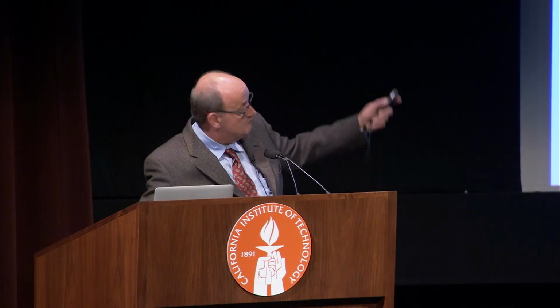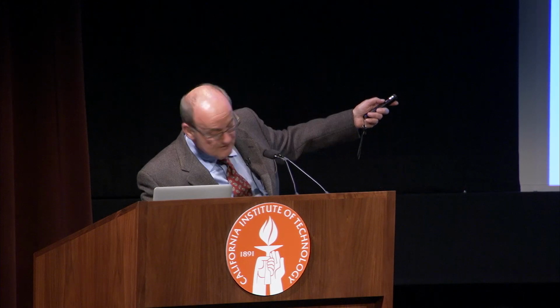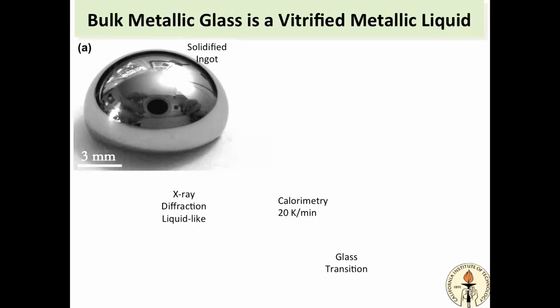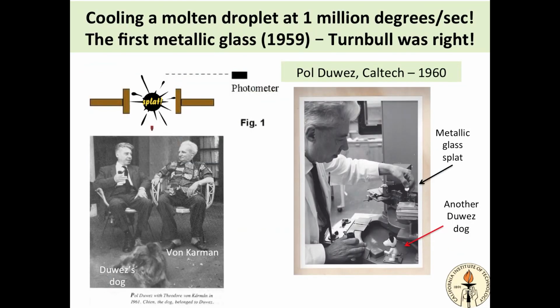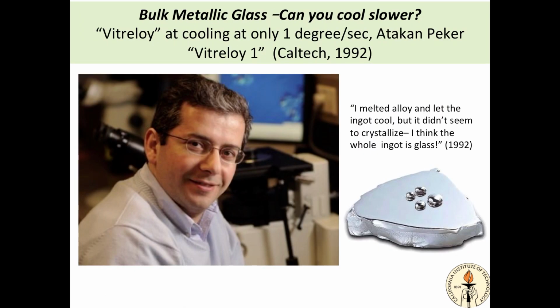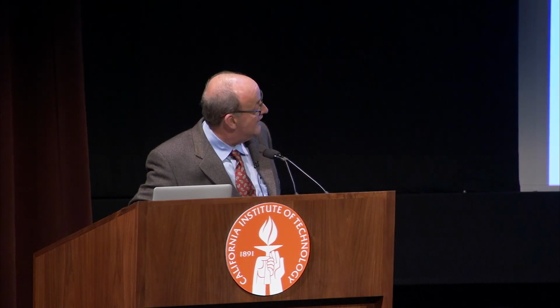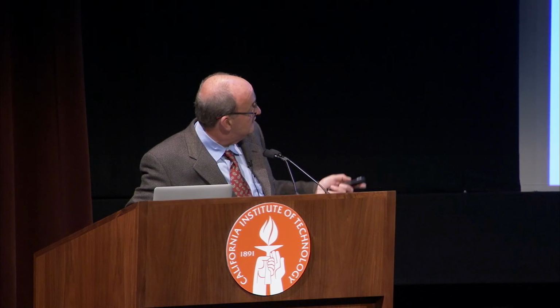So, of course, when we could make these things in bulk form and at low cooling rates, Atakan Peker was only cooling this at, go back, 1 degree per second. That was 1 million. He's only cooling at 1 degree. So we slowed the cooling from the Duwez experiment down by 1 million times, and we still make glass. And so now, how do you study these liquid metals?